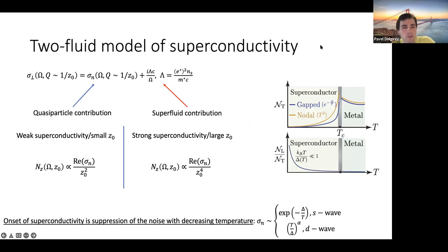Now let's think about actual superconductors and we want to write conductivity as the sum of normal fluid component plus superfluid. What is quite important is that I can consider two limits, say limit of very weak superconductivity. Then I immediately get that my noise will know about sigma_n, only about quasi-particle response. And the same holds for very strong superconductivity. I get that again, noise will know about sigma_n. And this is a generic statement that, in reality, this decoherence will be sensitive to actually quasi-particle response.